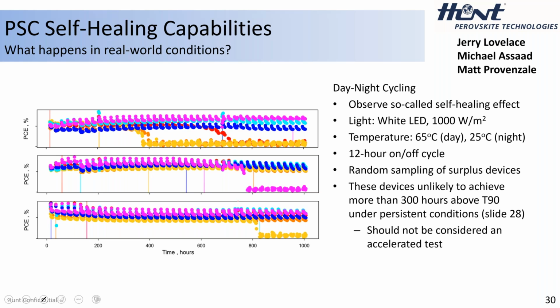To me, this highlights that self-healing capability, that when you're testing these perovskite solar cells in persistent conditions, high temperature and high light flux, whatever occurs, oxidation, whatever, ion migration, is irreversible and it accumulates over time. So these cumulative effects actually make the device fail faster. It's this chicken and the egg argument, right? Where if you incubate a chicken egg, you create a chicken. If I want to create a chicken faster and I want to put it in boiling water, I have a hard-boiled egg. I don't have a chicken. And so even though we feel like our accelerated lifetime testing is valid, there's perhaps a hard-boiled egg that gets produced every once in a while along with some chickens.